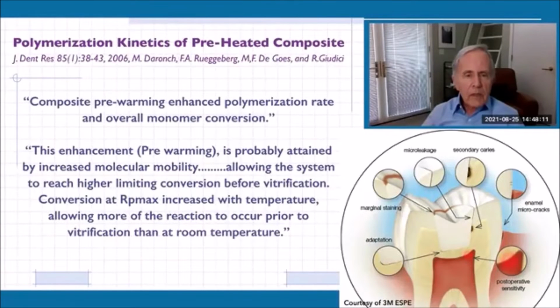So what is actually taking place when materials cure? Materials don't cure all at one time. They cure in stages. The first stage of curing, up until a certain point, is where a lot of the effects of stress take place. That point is called the vitrification point. And whatever conversion takes place prior to vitrification is the more critical one. So if we can do something to the material prior to vitrification, we can lower the stress in that material.